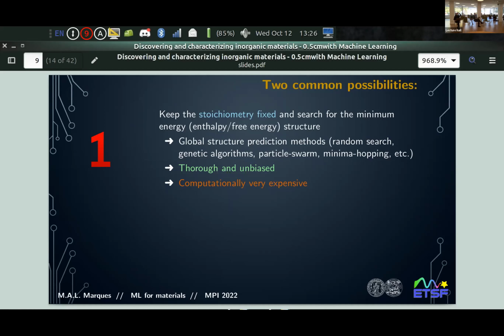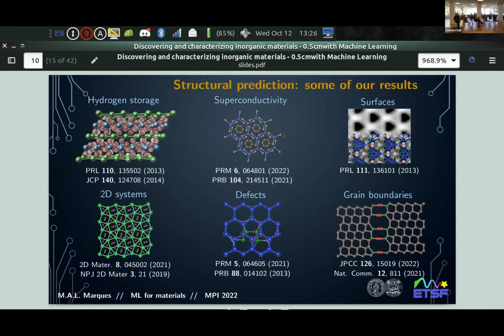We have done a lot of calculations using structural prediction. I just put here some examples, from materials for hydrogen storage to high temperature superconductivity at high pressure. Actually, the great success of these superconductors at high pressure is not really the superconductivity part, it's the structural prediction part, because they were all predicted before they were synthesized, and they were predicted using these methods.